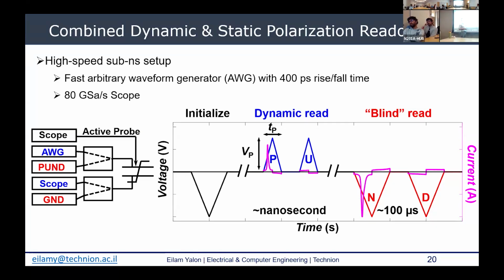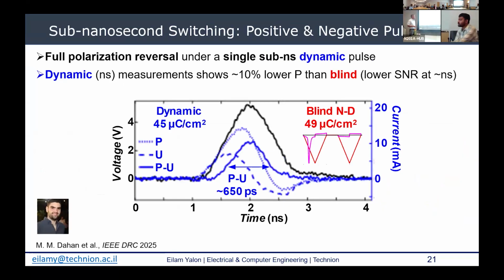So we get the dynamic measurement of the polarization in the nanosecond regime. And then we also add this readout in the opposite direction to get the amount of polarization that's switched here. And this happens at the longer time scale, where we know our measurement is accurate. So let's see what we get.